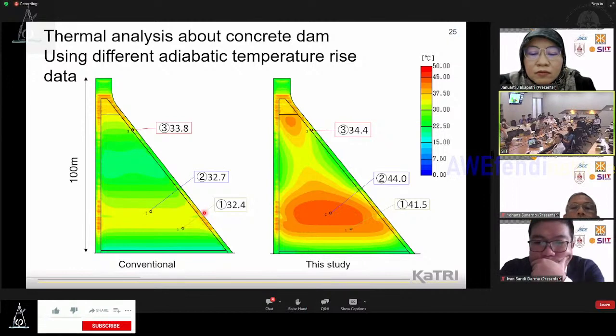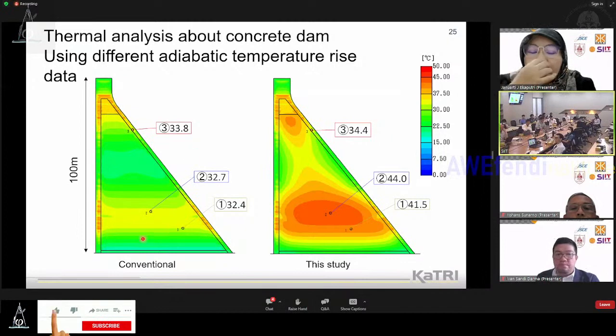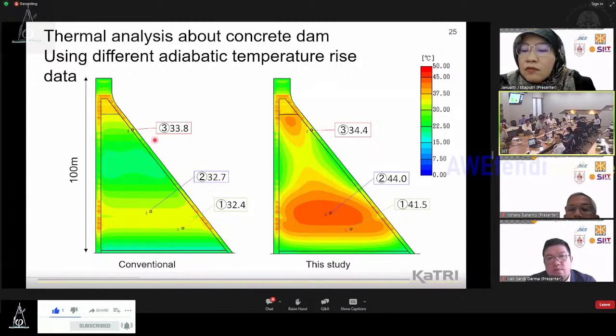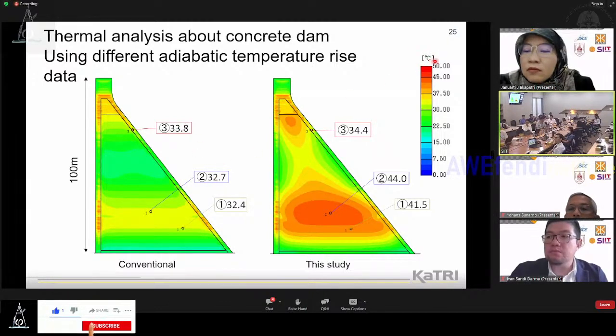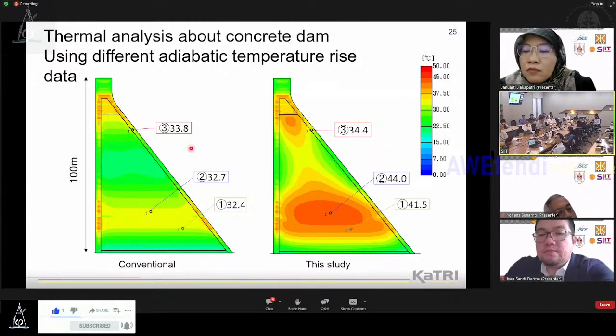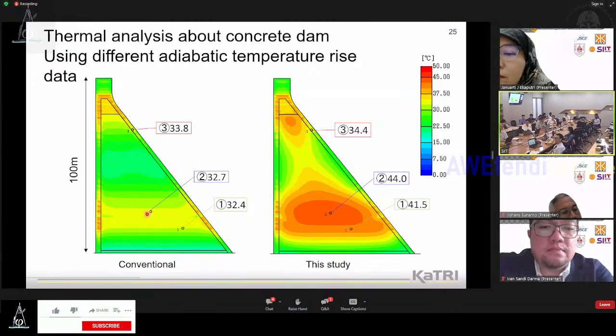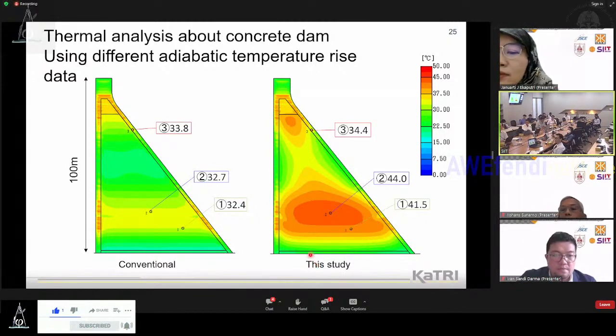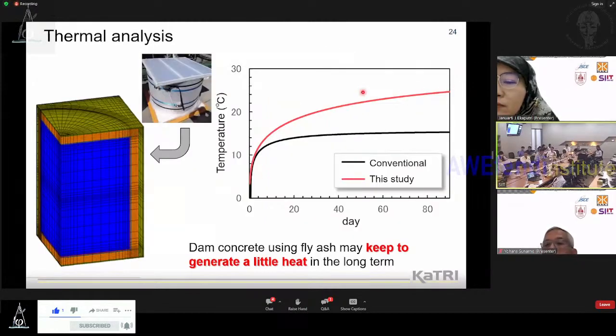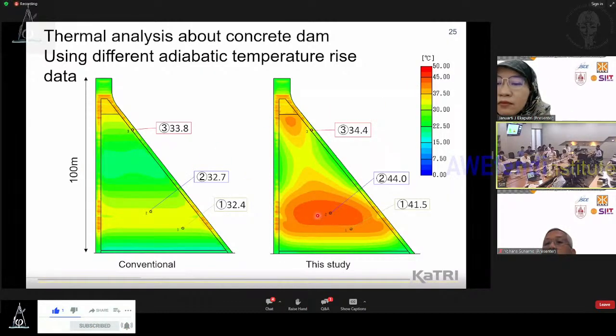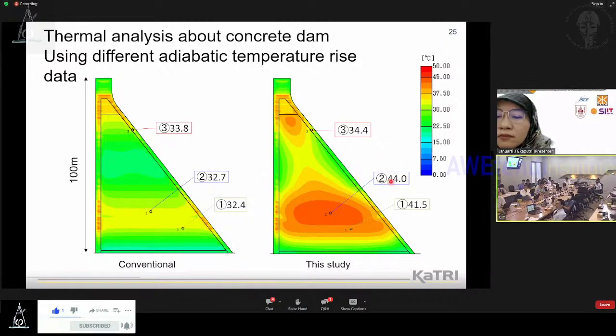This figure shows the result using conventional data. We usually use this equation, this data, and this value shows the maximum temperature at some points. Then we use this adiabatic temperature rise data for the dam concrete. It is about 10 degrees Celsius higher compared to the conventional data.